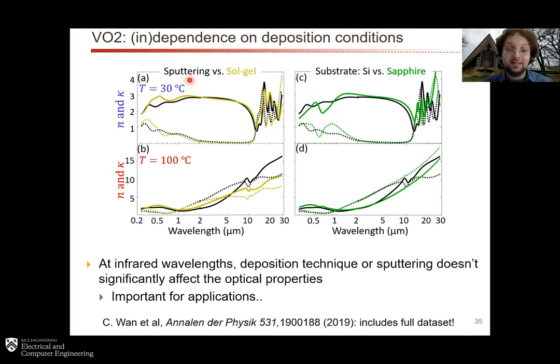Here is the N and K as a function of wavelength for sputtered films versus sol gel, but on the same substrate and the same thickness. Here we're keeping everything constant except the substrate is silicon or sapphire. And we do many of these comparisons. And one of the things that we found, which is very compelling to me, is that anytime you look below about 2 microns, you see that every sample is a little different.